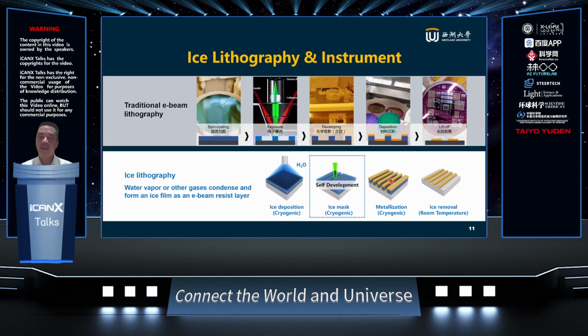And then you don't need to take them out to the chemical rooms because the patterns, the structures are already made. You can directly put them in the same vacuum, but with slightly different processing, deposit metals. And then in the final stage, you can simply remove the ice. This can be done, for example, by increasing the temperature to room temperature instead of very low temperature. And then you can easily make a very nice device without involving, at least not too much, chemical rooms or chemicals.